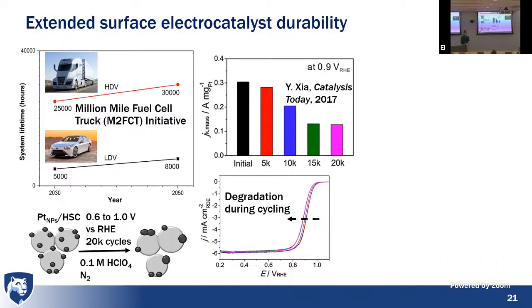And then as such, when you lose platinum from the system or the particles get bigger or they're touching each other, you don't have that exposed surface. We see this linear sweep voltammetry sort of shift to the left. And then we can measure this mass activity loss over time. So this is a paper from Georgia Tech looking at that at 20,000 cycles.